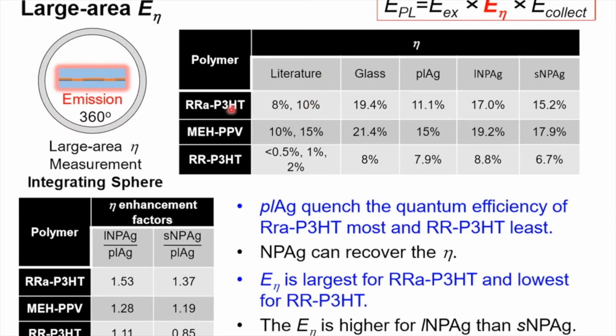If you look at the quantum efficiencies of the polymers on different surfaces, but first let's look at the literature values for regiorandom P3HT. Typically, it's around 10%. MEHPPV is about the same or slightly higher. Regioregular P3HT is a more crystalline polymer and tends to have more interchain interactions, so the quantum efficiency is lower. And so on glass, in our own measurements, compared to literature values, we found actually quite a high quantum yield of 19.4%. MEHPPV was a bit higher, but almost the same, and regioregular P3HT was about 8%.